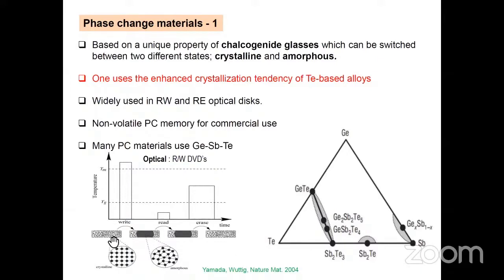The principle is that you basically start from a crystalline system. Here you can see the material with grains and boundaries. And as you raise the temperature, you will locally melt it. And as it cools down, it forms a glass, or at least an amorphous state, which is embedded in the crystalline matrix. Because of the difference in optical or electrical contrast, you can read it, and eventually you can rewrite on it or erase it by heating it up. In this case, the amorphous phase will recrystallize, and you have basically erased the data.